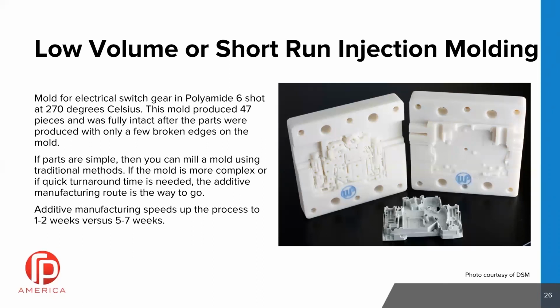Sometimes a little bit of post-processing is required, a little polishing of the parts helps. But other than that, if you use a little bit of mold release, these parts come out great. You do have to, it's a slower process. Typically you're blowing air on the molds before or after each run, so it could be a minute in between cycle times. But when you're only doing 30, 40 parts, because that's all you need, then that time's not too bad.